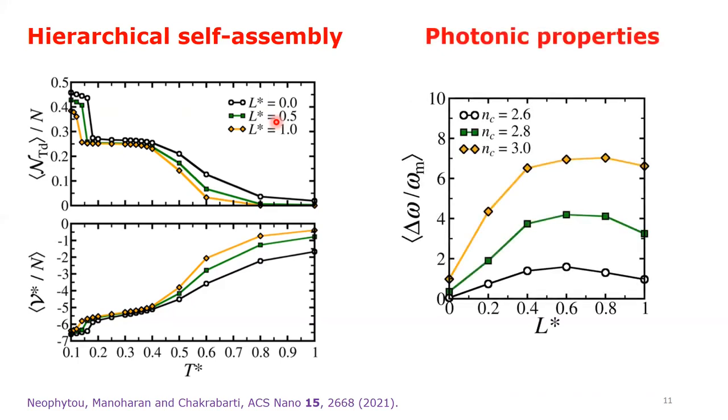For the segmented rod connected diamond structures, we find that both the cubic and hexagonal polymorphs support a complete photonic band gap